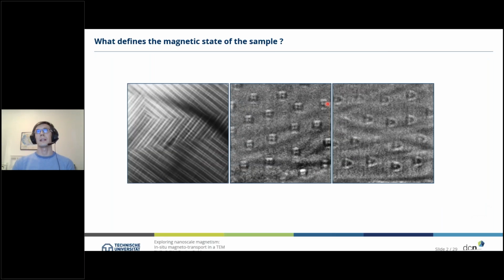So what defines the magnetic state of a sample? You see here 3 Lorentz TEM images of exactly the same sample, but of course the image looks completely different, right? On the left-hand side, you see some stripe pattern. These stripes are perpendicular to each other. You have bright and dark contrast. And then in the central image, you see rectangular features popping up. They are as well regularly arranged. And on the right-hand side, you see features which are more spherical or half spherical, half elliptical in shape, and are as well quite symmetrically arranged.